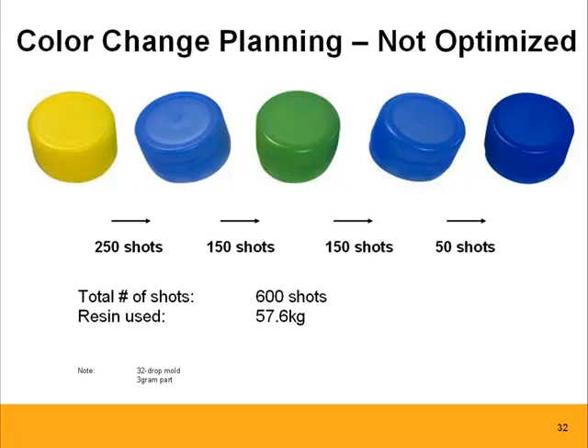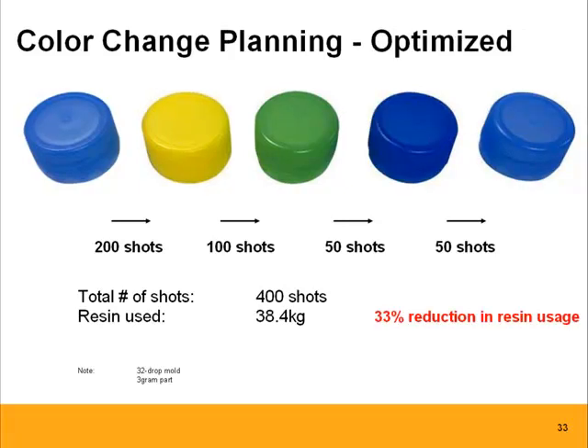An optimized sequence, just looking at the colors, would be going from the light blue to the yellow, from the yellow to the green, then to the dark blue, and then to the light blue. And just by changing the sequence within that given day of these parts, we're using 400 shots or 38.4 kilograms, which is a 33% reduction in resin usage. And again, depending on the part weight and everything else, these numbers change, but I think it gives you a pretty good idea how important planning ahead is when it comes to color changes and scrap reduction.